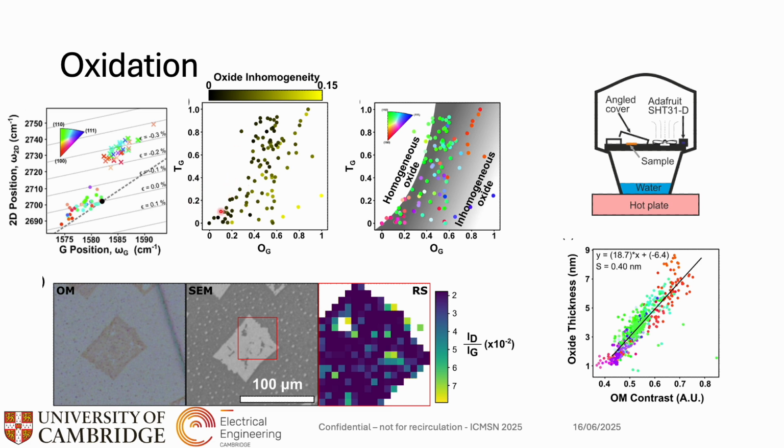Moving on towards thinking about how it actually transfers, we can map Tg, and this is the percentage or the fractional value of that graphene that's successfully transferred from that which is grown. So we take each one of these individual islands, we measure where they are, and then we transfer them and measure in the SEM how much of that graphene is actually transferred. And we can compare with the oxide measurements from optical microscopy and the transferred measurements from SEM to see what sort of trends exist. And you can see a reasonably unsurprising trend that the more the interface is oxidized, the more transfer we get. But it's not necessarily so clear.